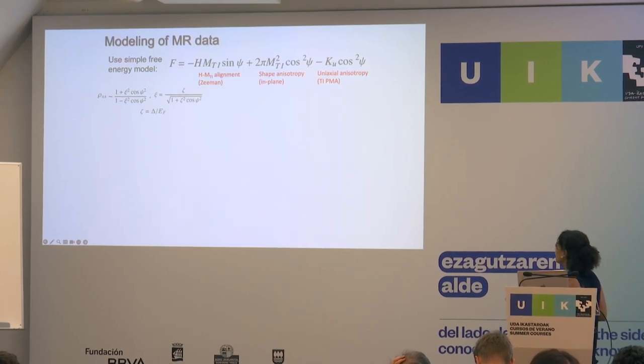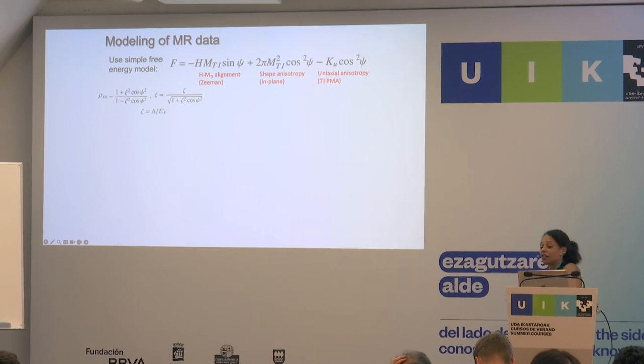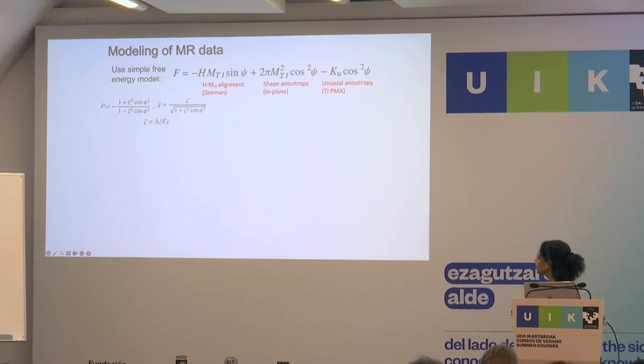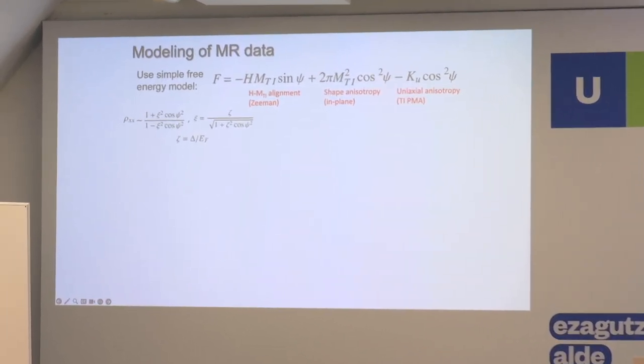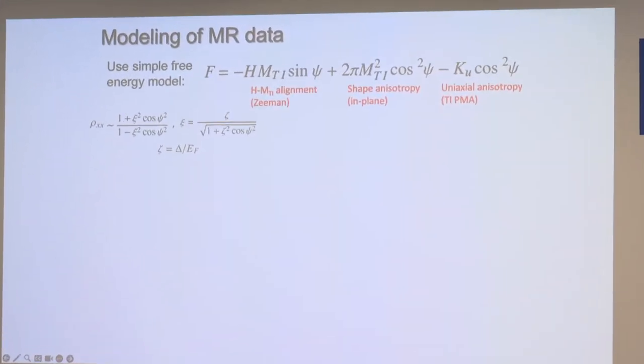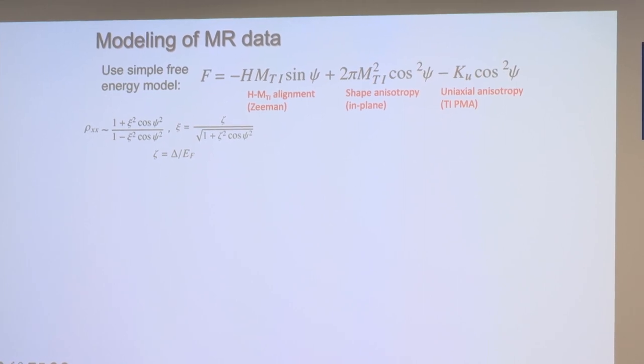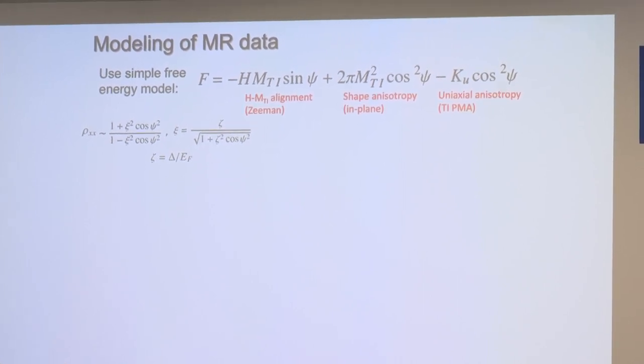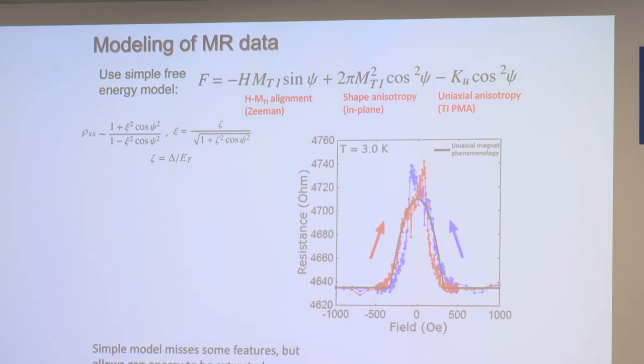And so we can model this sort of behavior just using a very simple free energy analysis, which takes into account the alignment of the magnetization, the shape anisotropy, and the uniaxial anisotropy of the topological material, using the Stoner-Wohlfarth formula that was published earlier. When we do the free energy calculation, we can see the basic shape here, but you can see we miss these features at top. This is because this doesn't take the YIG into account at all. This just takes the bismuth selenide into account.